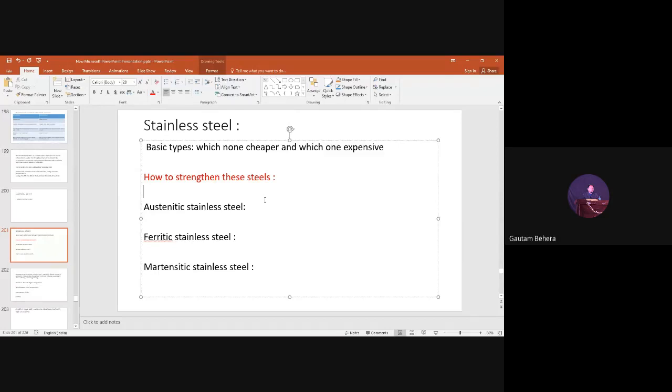The ferrite is BCC. And another point, some exception in case of austenitic stabilizers, like cobalt. Cobalt is an austenitic stabilizer. The cobalt crystal structure is HCP basically, up to about 440 degrees centigrade, but above 440, like 450, it again becomes FCC. That means cobalt shows allotropic modification. So cobalt is an exception where it is HCP, but it stabilizes the austenite phase. Silicon, aluminum, okay, fine. These are some exceptions.